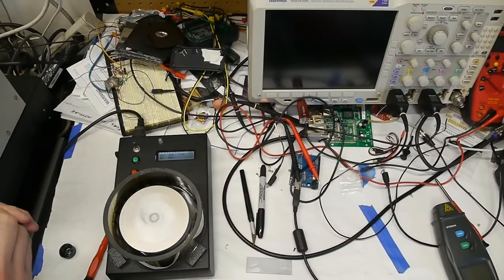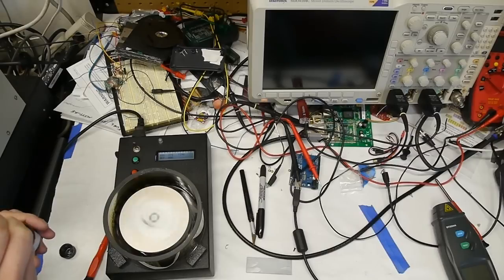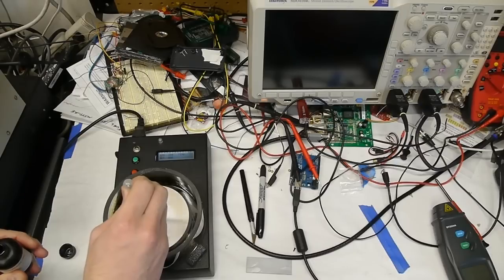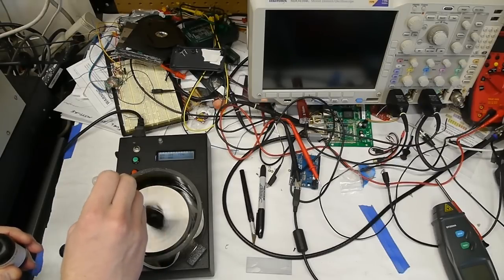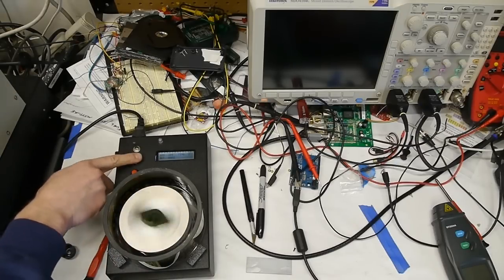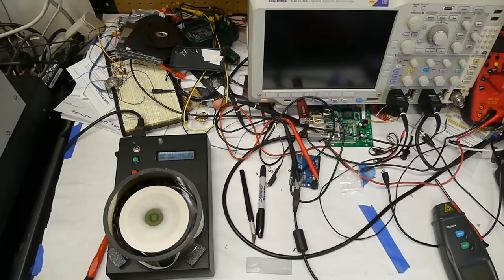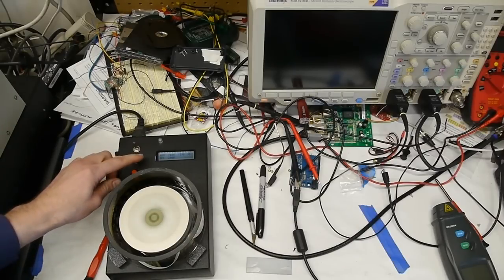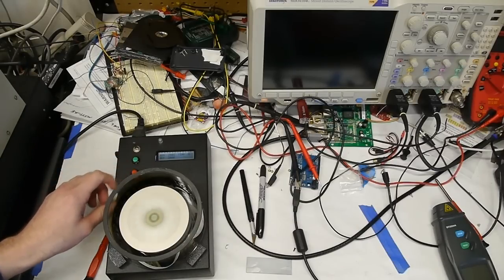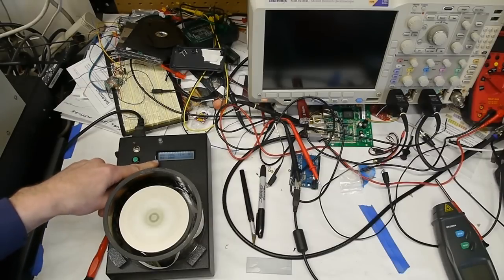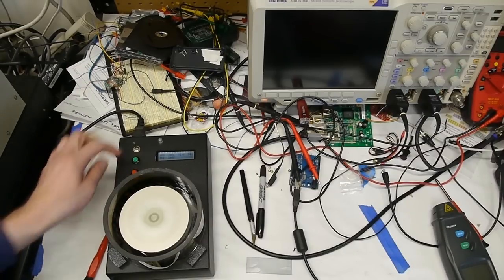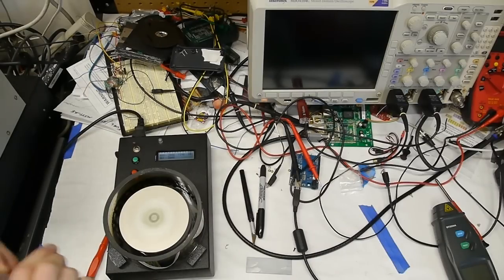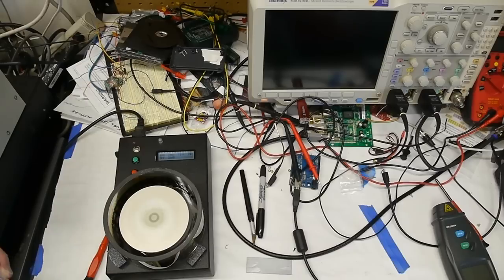So I'm going to use this liquid, which is a photoresist. I realize I'm doing this under shop lighting so it's not going to be really useful, but this will just give you the idea. And then we press the green button again, and the machine goes through a very controlled acceleration up to about 3000 RPM. When it reaches 3000, it holds the speed and it's counting up in seconds. The whole idea here is that we want this process to be very repeatable because we want a very consistent, even layer of photoresist.